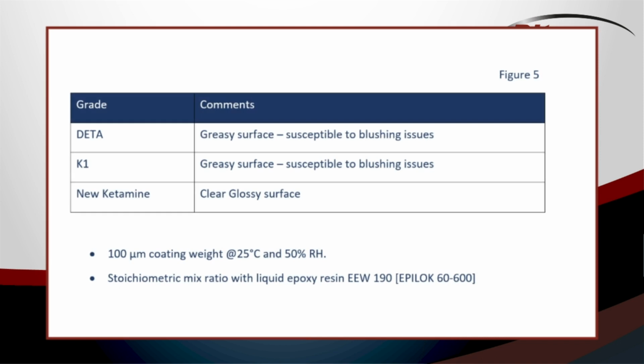It's evident that poor compatibility, exudation and surface migration of free amine can result in blushing and blooming issues, which offer aesthetic concerns, but the cosmetic defect is more an illustration of the fact that the intended or desired reaction hasn't fully occurred. These problems can also influence overcoatability and subsequent intercoat adhesion, which in turn can alter mechanical properties and chemical resistance. The new ketimine grades offer enhanced compatibility and they vary in terms of their surface appearance, with a moderate improvement to the surface film to a significant advance based on selected grades from within the range.